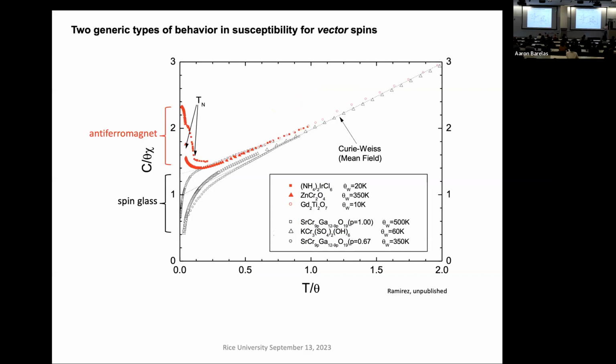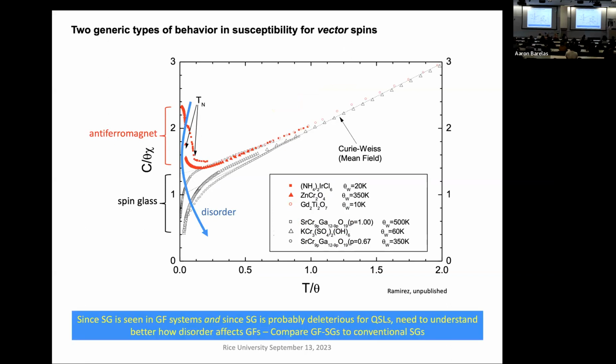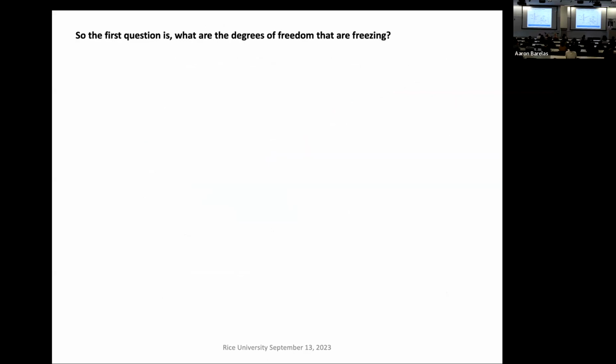So there are essentially two types of behavior that can be observed in frustrated systems. One kind can either go up or can go down. When it goes up, it always becomes an antiferromagnet. When it goes down, it almost always becomes a spin glass. This is a kind of reduced scale with a whole bunch of different compounds, different interaction strengths, lattice symmetries, spin sizes. And the general trend is that disorder induces this type of behavior. It's not surprising since it's a spin glass. So we're going to try to understand disorder.